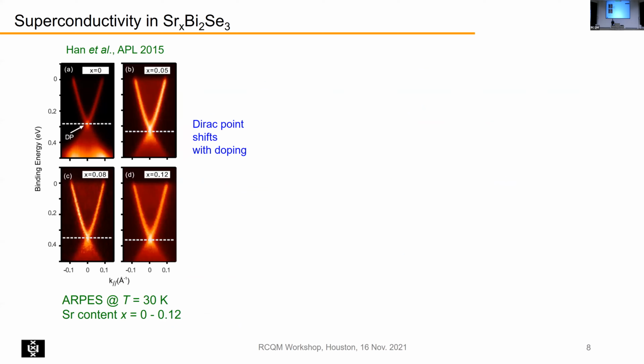Then, of course, we are interested in the topological properties of the materials. So one can do ARPES. Here are data at 30 Kelvin. This is for a doped system. Here you see the Dirac cone. So this is the pure bismuth 2 selenium 3. Well, here you see only the surface states. If you would use a different energy, you would also see the bulk states. If you dope, or you intercalate, so 0.05, and here higher dopings, then the Dirac point shifts. So when you put the strontium in there, it still has the topological surface states.